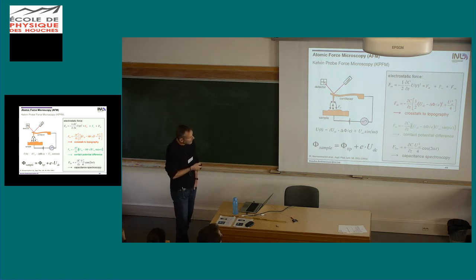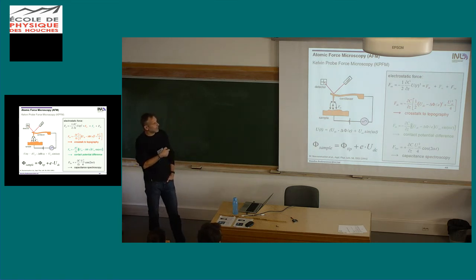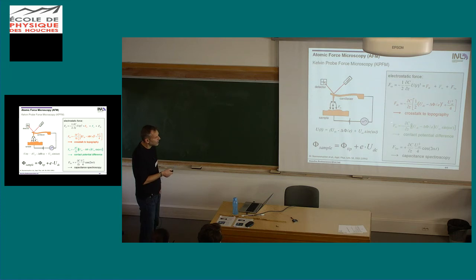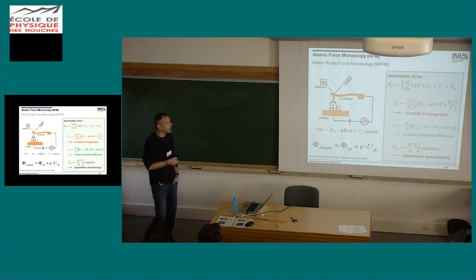So then in the next step we apply a controller, and the input for that controller would be that signal. So now we use a controller that reduces this oscillation to zero, which means this force disappears. And this disappears exactly when the DC bias that we apply, this part here, corresponds to the contact potential difference, to the difference in work function between the tip and the sample. So this term becomes zero, the force gets zero, there's no more oscillation at this frequency, and we detect this by using the lock-in on the photo detector here. So the controller adjusts the DC bias to the contact potential difference.